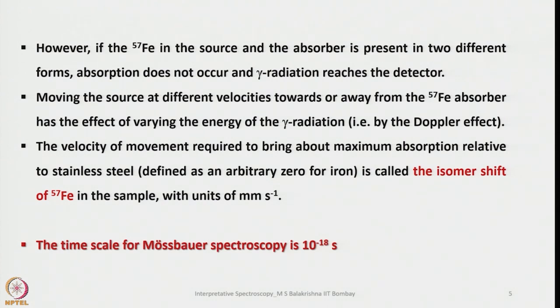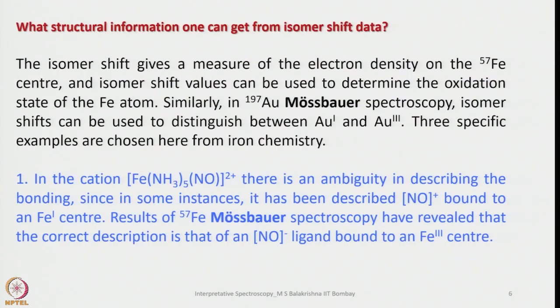The velocity of movement required to bring about maximum absorption relative to stainless steel, defined as an arbitrary zero for iron here, is called the isomer shift of 57 iron in the sample, with units of millimeters per second. And of course, the time scale for Mössbauer spectroscopy is 10 raised to minus 18 seconds. And what structural information one can get from isomer shift data? So this isomer shift data gives a measure of the electron density on the 57 iron center, and isomer shift values can be used to determine the oxidation state of the iron atom. So that means it gives electron density as well as the oxidation state of iron atom.